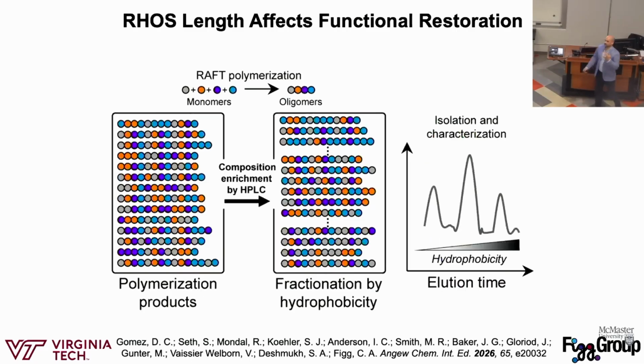But the big thing is, we're just doing a single polymerization with so many different sequences, and we don't actually know what the winners and the losers are in this composition stoichiometry that we're adding. So what we did next is we took our polymerization and we shot it through an HPLC with a C4 column or C18 column. By fractionating by hydrophobicity, we can collect different fractions of that single polymerization and understand how the composition from that polymerization is affecting the binding, and whether there are stronger binders in solution compared to weaker binders in the solution. Again, this is a single polymerization from a round-bottom flask, shoot it through an HPLC, and we fractionate it that way.